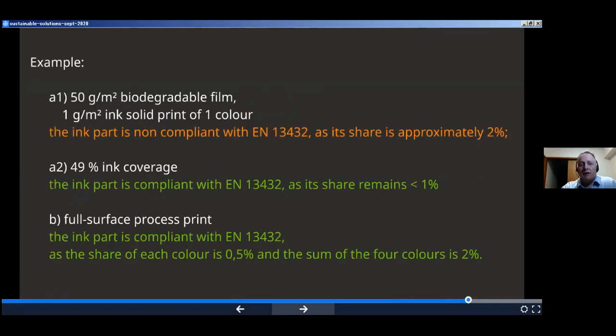So for example, if we use 50 grams of biodegradable film and we want to print 1 gram per square meter of one ink, this will not comply with the conditions of biodegradability, because this one single ink represents more than 2%, and the limit was 1%. But if we only cover half of the packaging, the ink already is compliant because it remains below 1%.